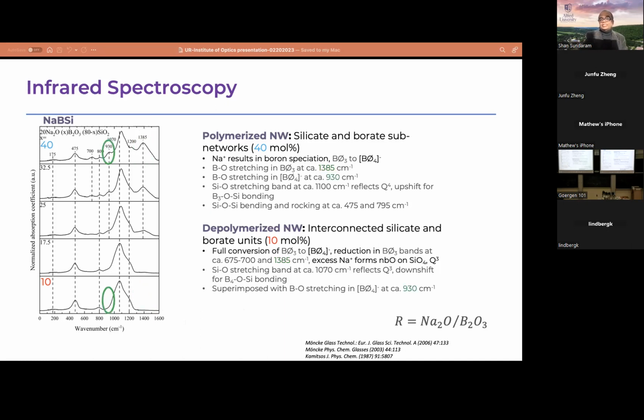So moving on with the same spectroscopy data, if you look at the 930 centimeter inverse band, this is dominantly due to boron oxygen bond stretching in BO4 tetrahedra structure inside the piece of glass. So similarly, you can see by the time we come to 10%, the shift has happened here. This is dominated by silicon oxygen stretching bond rather than boron oxygen stretching dominating the tetrahedra in the polymerized form. We see the same trend continuing, looking at other features.